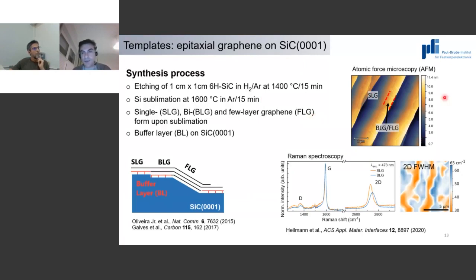So it's not. What we see here in the AFM is that usually what happens, so you have atomically flat terraces, which you can see here, and in between these flat terraces, we have a step edge. This is coming from the silicon carbide, so it's represented in this image here, where I have the silicon carbide in blue. So basically, you have an atomically flat terrace, you have a step facet, and the next terrace comes here.